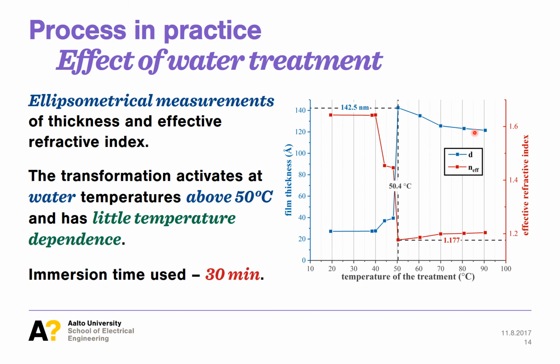With the specified immersion time, the process activates at water temperatures above 50 degrees. But there is very little dependence on the film properties after this temperature. Another big advantage of this water treatment is that the transformation saturates at a certain state. After the water has worked its way through the film, further time spent in water has negligible effect on the film structure. The saturation in respect to temperature and time simplifies implementation of this technique even further. In additional experiments, we have also confirmed grass-like alumina formation from the films atomic layer deposited at 80 degrees Celsius, which makes it applicable for many plastic substrates.